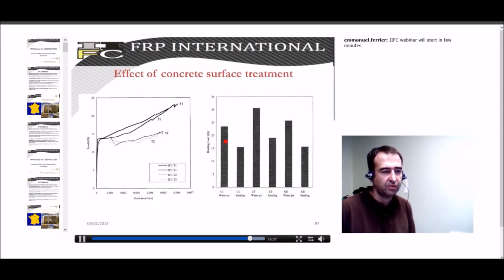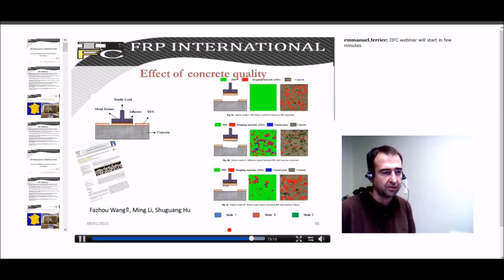With the same system, if you use water jet, you can observe that the ultimate stress is much higher than the one obtained by only sanding the surface. It means that the bonding is more complex than we thought, that the concrete preparation should be looked at very carefully, and maybe such surface preparation should be introduced in the model, because for now nobody really cares about how the surface is prepared. We need to prepare it, but we don't really know if this affects the ultimate bonding load.